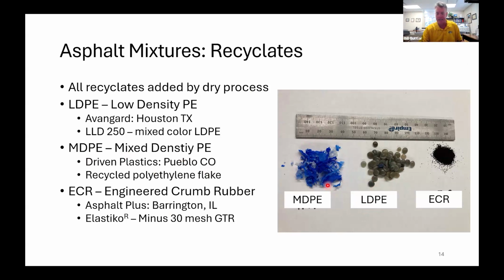From another partner, Driven Plastics out of Pueblo. They have a shredded plastic. They have all sorts of different shreds and grades. We chose the middle of the road product, which was their mixed density polyethylene shred. And then, of course, this 30 mesh engineered crumb rubber product that we're very familiar with in Missouri. We have a spec for that and similar dry process rubber. Those were all used. And then by the time you looked at SMA versus dense graded versus control and PPA, SBS, that's how we came up with the 9 sections.